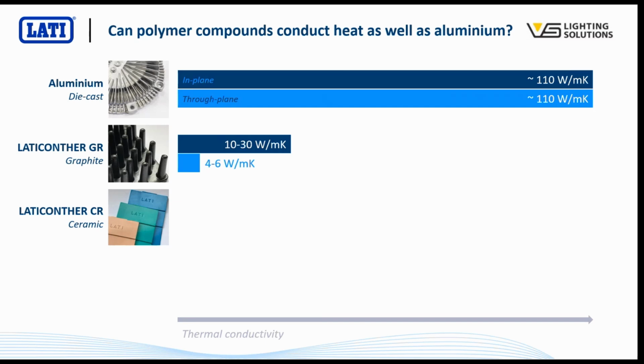The first thing we'll note here is that the in-plane thermal conductivity of graphite-filled plastics is generally in the region of just 10 to 30 watts per meter Kelvin. So at best about a third of what we can achieve with aluminium. But because the graphite platelets have a high aspect ratio, their XY dimensions are much larger than their Z direction. They're much longer and wider than they are thick. That means that very much like glass fiber reinforcements, the graphite material will align to a certain extent during the injection molding process. And much like how that alignment of the glass leads to some directionality in mechanical performance, with the graphite compounds, alignment of the graphite leads to some directionality in the thermal conductivity. So in this case, we see a big reduction in thermal conductivity through the thickness of the part versus along the flow path of the injection.